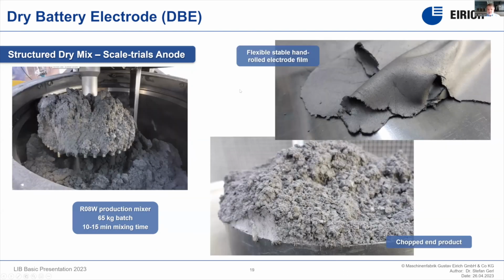The same can be done on the anode side. So here we see on the left side, this is a fibrillated mix in the large-scale pilot machine. We are chopping this machine product then into this dosable material. And out of this, we can then form, let's say, an elastic film with good flexibility. You see this already on the bending radiuses, that this film has a good inner adhesion.